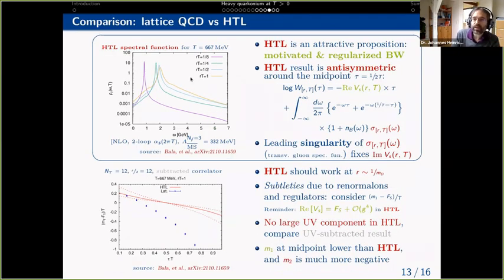And something else would mean that we go back to the hard thermal loop calculation by Bala et al. If you look at the spectral functions that are coming out of hard thermal loop, then we have these local Breit-Wigners sitting on some continuum here for almost 700 MeV and 4 different distances. So this is attractive because it should be a Breit-Wigner, it should be somewhat regularized. And since it's based on weak coupling, you might have a try with this.